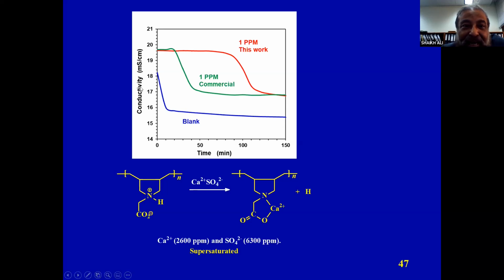Now, this here is conductivity. When the conductivity decreases abruptly, that means calcium sulfate forms and the ionic concentration decreases. That indicates the formation is up to here. It is up to 70 or 80 minutes.